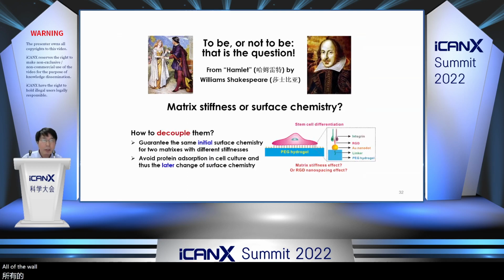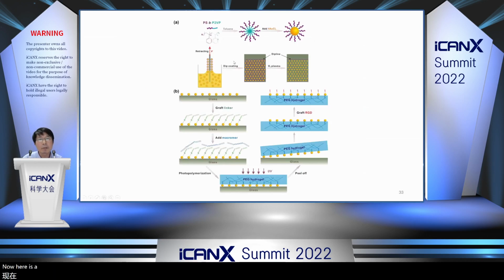So we think that the key is that we should design a very strict experiment to decouple the matrix stiffness effect and the potential surface chemistry effect. And our unique surface patterning technique can accomplish such a very tough task. Now here is the schematic presentation of our experimental procedure. We first use block polymer micelle nanolithography to obtain the gold nanoarray, and we transfer the gold nanoarray to the PEG hydrogel, and we link RGD and then we culture cells.